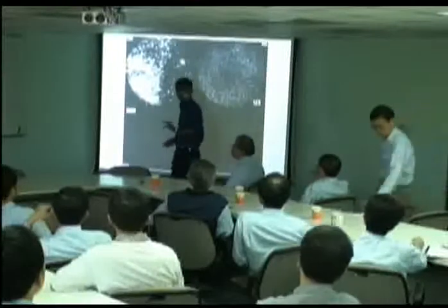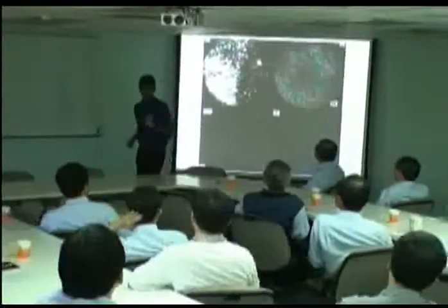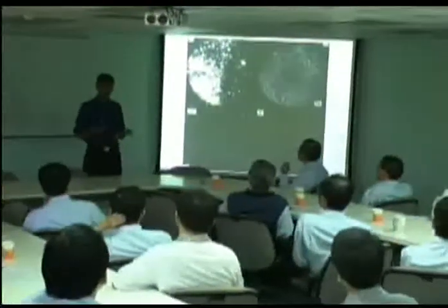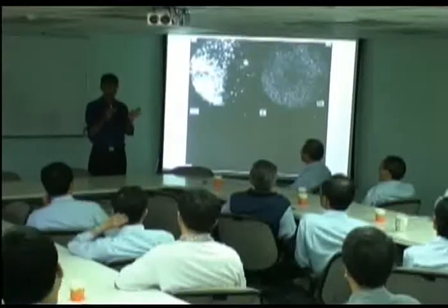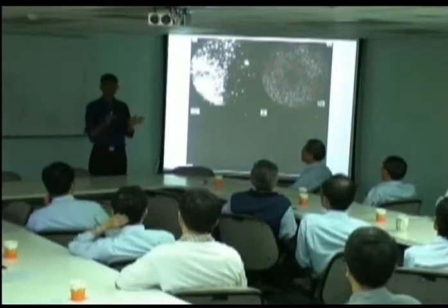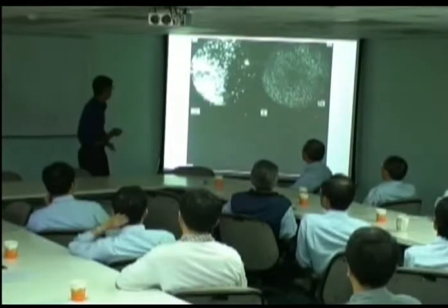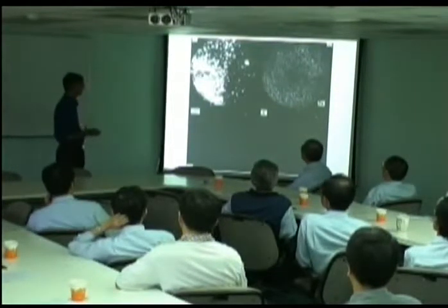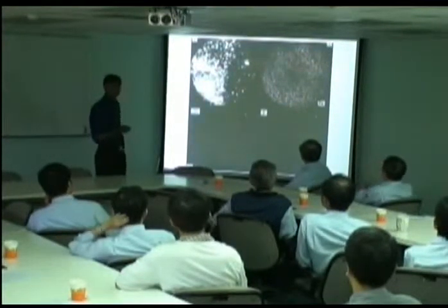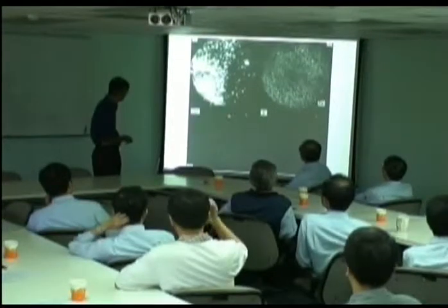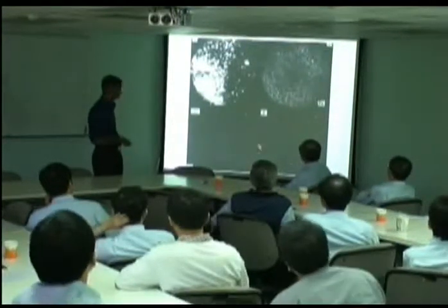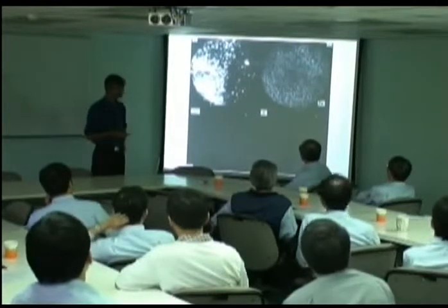Good. Okay, so we're going to look at individual atoms. These are images taken using a field ion microscope, where you can see individual atoms, and you can identify what those individual atoms are. And the first image here shows you an interface between the bainite on this side and austenite on this side. So all the atoms are being imaged here. Here we are only imaging the iron atoms. Here we are only imaging the silicon atoms. And here we are only imaging the carbon atoms.